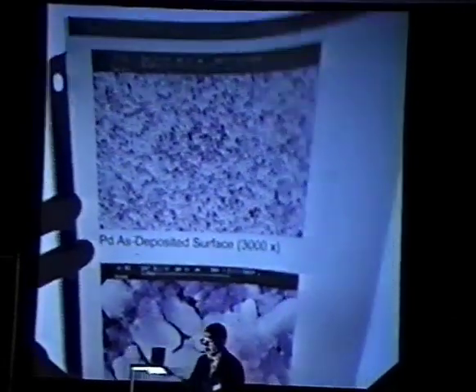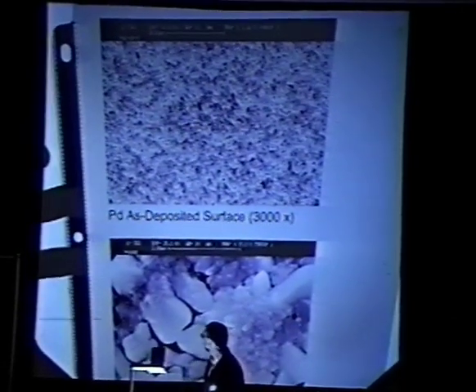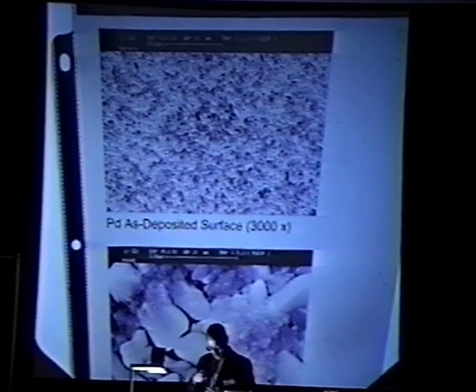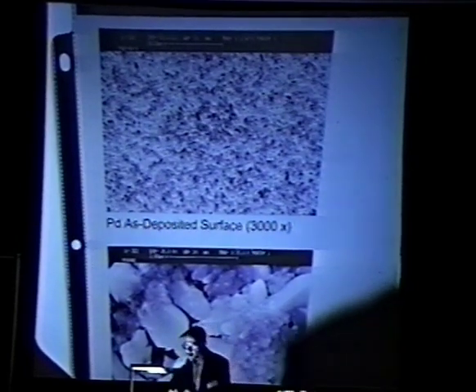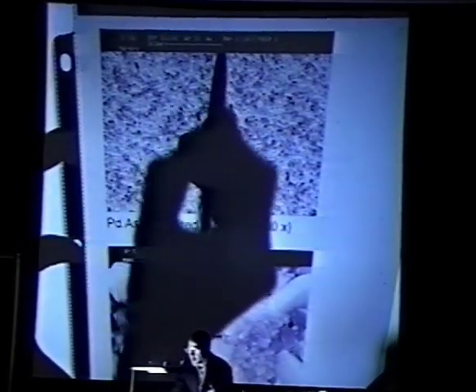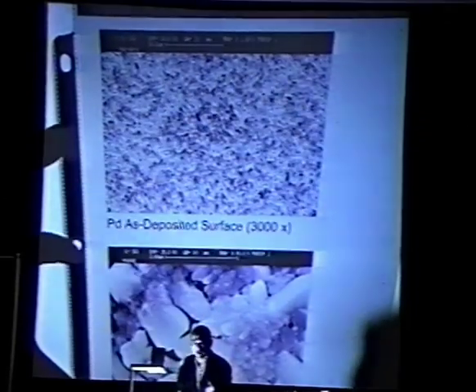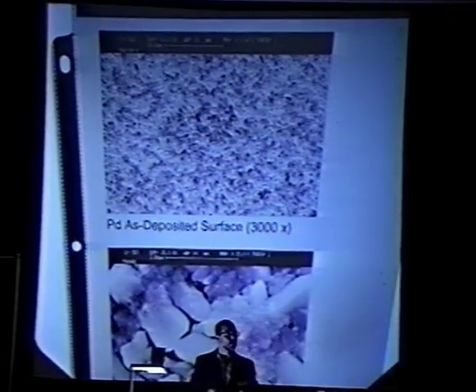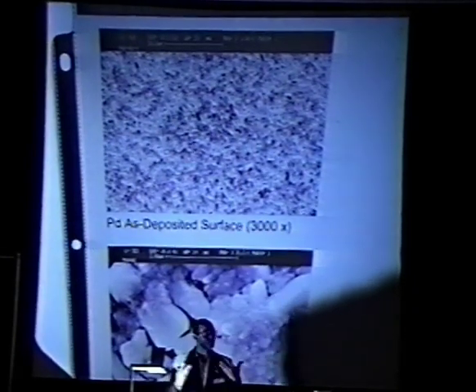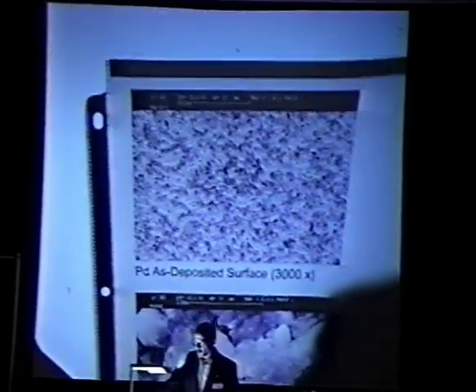This is a typical photograph of an as-deposited film. We made several of these. At the top, you can see the basic scale on this. This is a 10 micron scale running from here to here. So the basic grains, you can see the largest ones are no more than 2 microns in size. And they're basically uniformly polycrystalline with what's called a log normal distribution throughout.